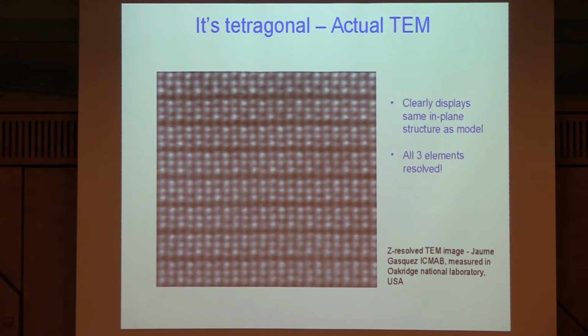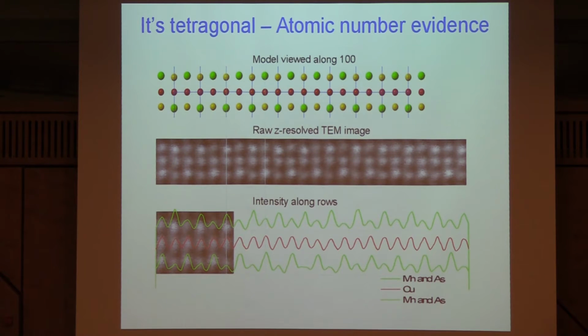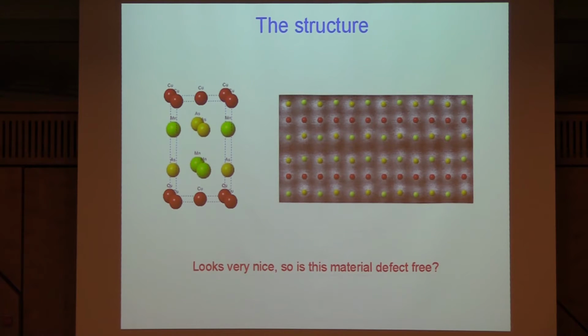So it's pretty clear that we were on the right track, but just to confirm it, if you actually look at the integrated intensity along the rows, you've got this nice uniform amplitude here, and then you've got this varying, oscillating amplitude, bi-amplitude if you like, along the rows where you get manganese arsenic, manganese arsenic, manganese arsenic. So this actually pretty much put the nail in it for us. We were absolutely sure that we had the tetragonal structure, and that the atoms were in the place we thought they were. So this is great. Beautiful structure, overlays very nicely, looks very nice.